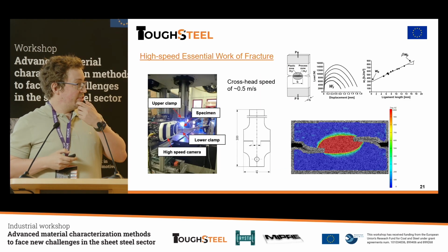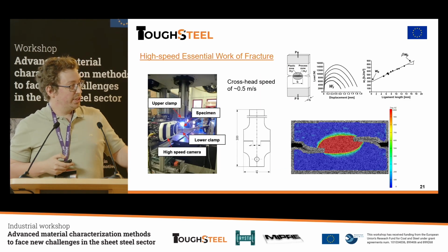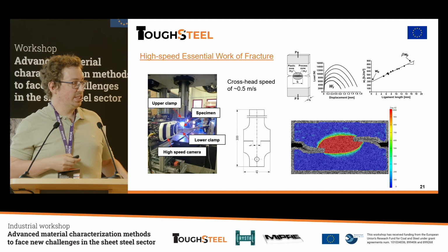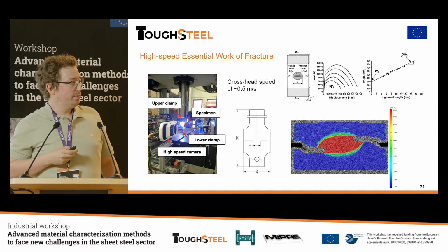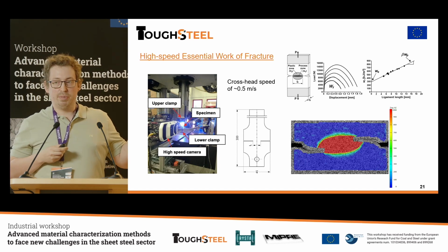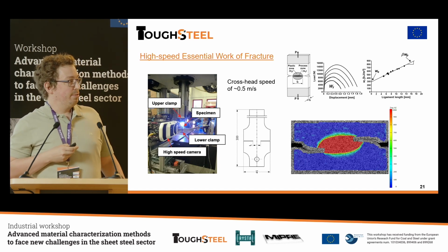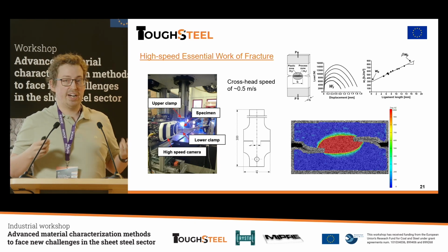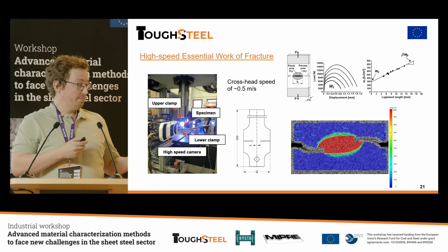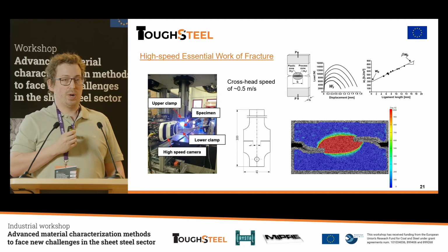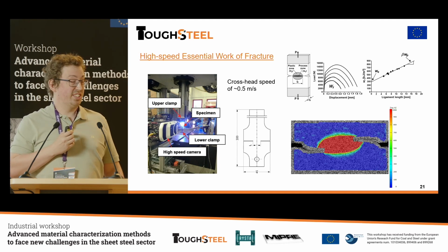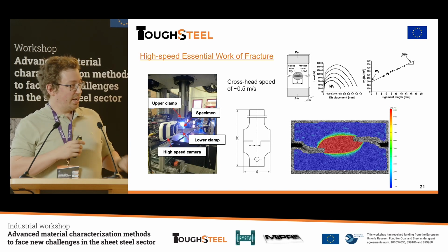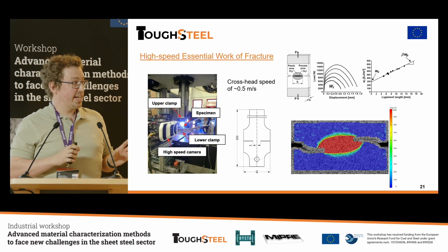So I decided to investigate that as well, using the essential work of fracture at high speed. It's been done by Golling before, but I tried to do it for one of the materials here. I just tested the TBF material. And the crosshead speed is 0.5 meter per second, and it can be compared with the published results when they tested with 1 millimeter per minute. So this is 30,000 times faster. But otherwise, the methodology is the same.